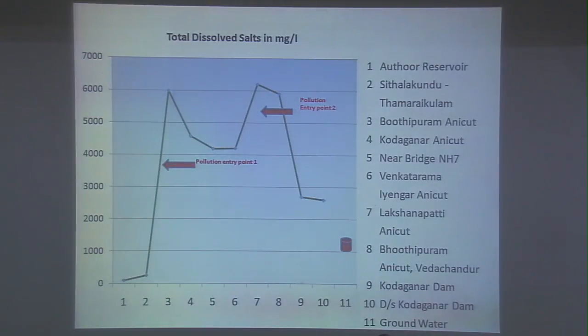You can see the test results of the samples collected from the 10 places have been plotted. You can see 2 places where the TDS value has gone above 6,000. Normally the reservoirs will have TDS less than 1,000 only. All our 14 reservoirs have TDS less than 1,000 only. And here the Kodaganar River, Kodaganar Dam, has water with TDS more than 2,000. That is the problem of the shutters, non-operation of the shutters.